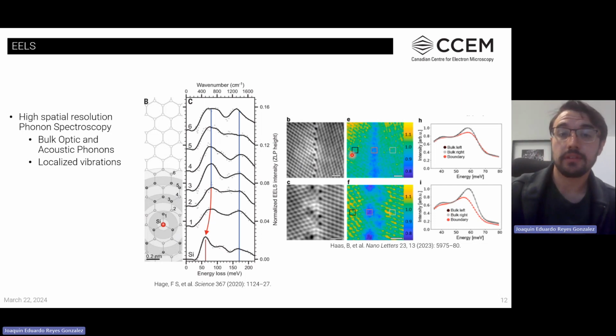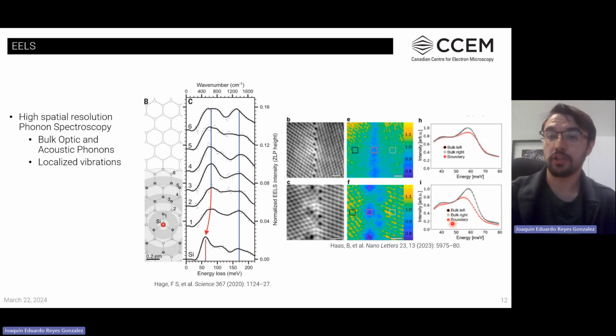Here we have these squares associated with the spectra you see on the right. As you can see, with the capabilities of the Nion microscope, it is possible to identify intensity variations associated with these structural defects, and also red shifts or energy shifts of the vibrational frequency of the modes localized in the particular regions we observe. This map is given from, I believe, this region at 60 milli-electron volts.